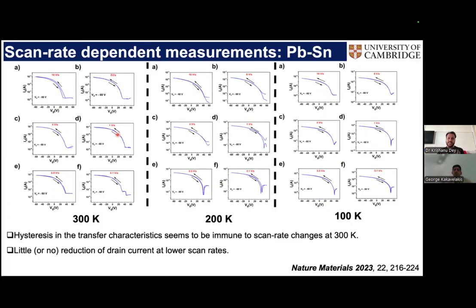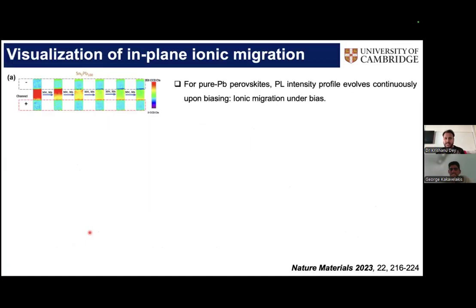But if you look at the lead-tin perovskites, you see that there's very little change in the hysteresis at room temperature, which is great. And again, for the lower temperature, we expect them not to have any effect anyway. But more importantly, there is very little change in the drain current as you go down from higher scan rate to a lower scan rate. So again, both of these things are telling you that in the tin-containing perovskite devices, you have low ionic screening effects. And then we wanted to visualize that.